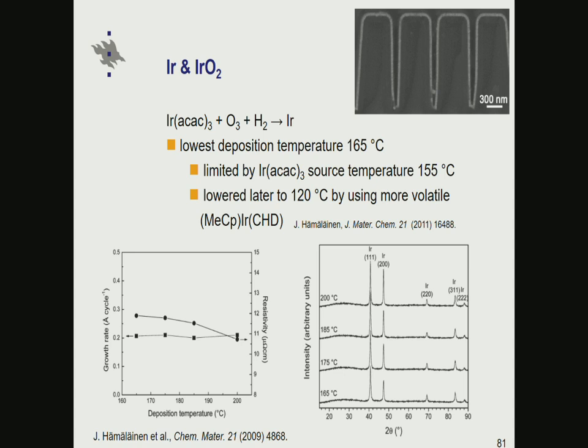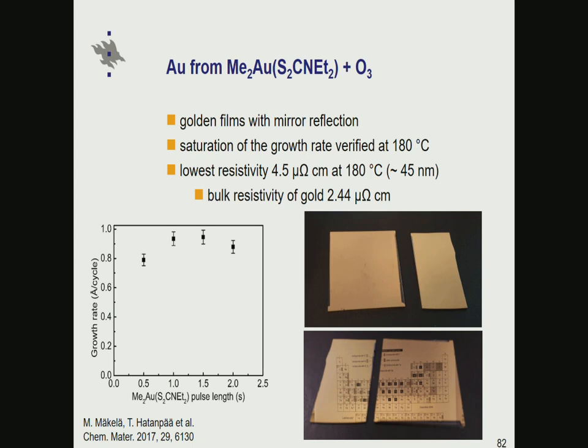So by playing this chemistry both on the metal and non-metal side, one can tune the proper deposition conditions for metallic iridium. And finally, the ozone chemistry eventually came to our dream: we eventually could deposit gold. That has been a kind of passion for us for quite a long time, to deposit metallic gold by ALD, and it required the synthesis of, I guess, 20 gold precursor candidates, and eventually we found one which is thermally stable enough that we could volatilize it nicely. It doesn't decompose until 250 centigrade, and once we used that together with ozone, we could deposit gold films in a saturated manner at 180 centigrade.